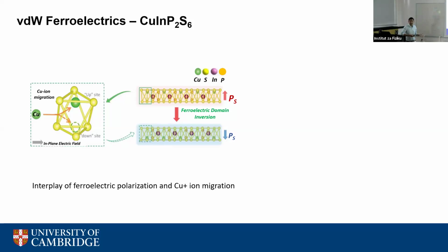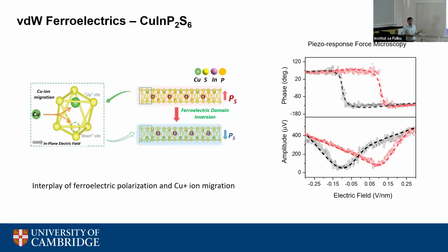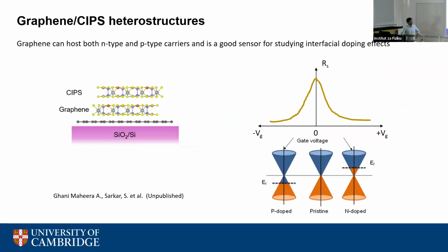So it's kind of an ionic semiconductor and a ferroelectric, which makes it a ferroionic material, which makes it quite difficult to understand: is it the ionic motion which is giving rise to memory? Is it the ferroelectricity giving rise to memory? So we wanted to understand what the contribution from these effects is in our devices. These are standard PFM microscopy loops where you can see the ferroelectricity in these crystals. These are the phase and amplitude loops. So the goal of this project was to look at when you place CIPS, a ferroelectric, on a semiconductor, does it dope the material?